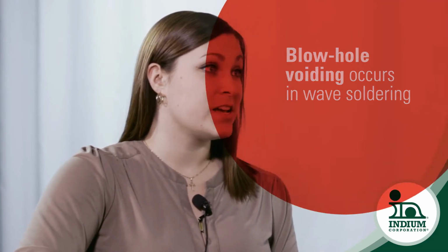And the last type of voiding is blowhole voiding that occurs during wave soldering when the solvent isn't completely evaporated in the flux and it pools up in the holes, and when the hot solder hits it, it explodes and creates a void. Kim, when we talk about voids, the other concern we have is, is it a defect or is it only a symptom? That's going to basically guide us in action whether we're going to do rework or it's cosmetic and we should just, as best practice, leave it alone. How do we determine that?